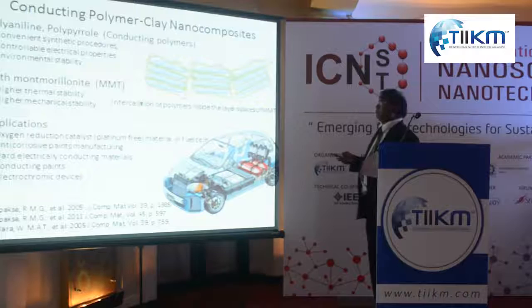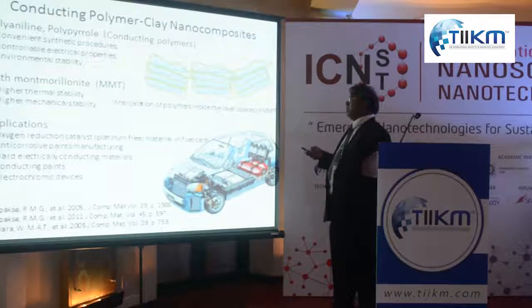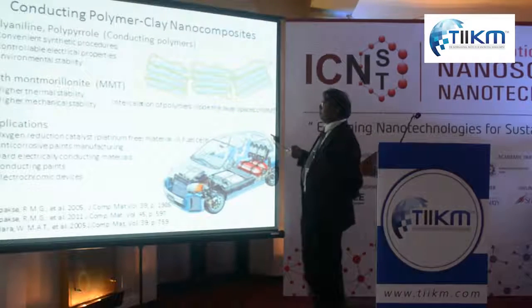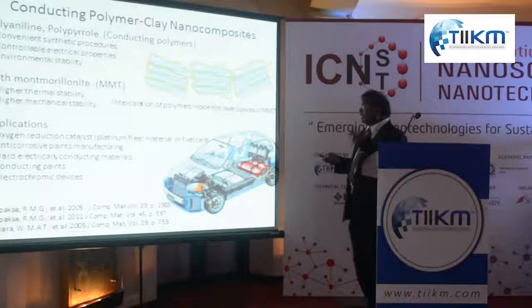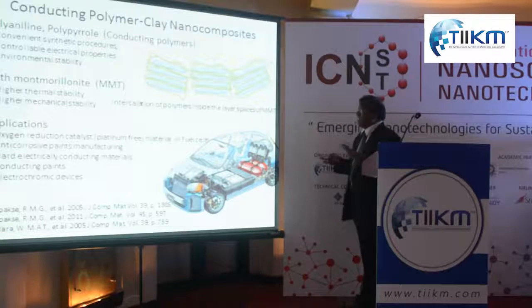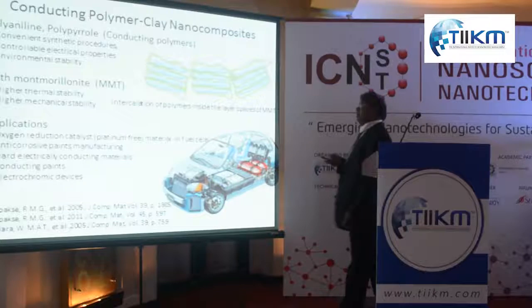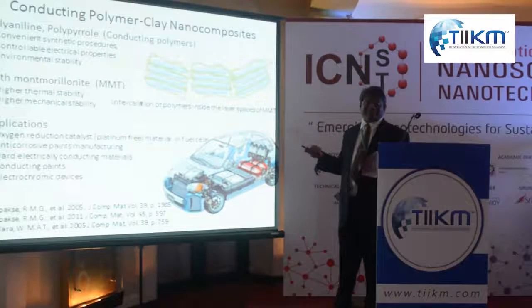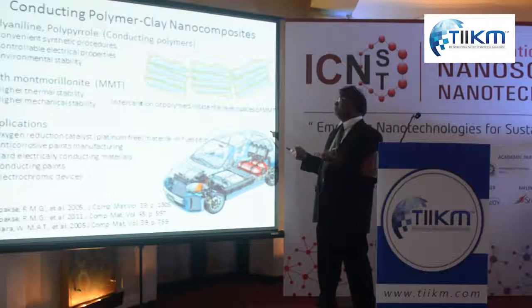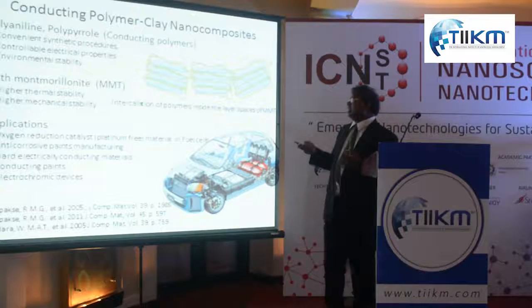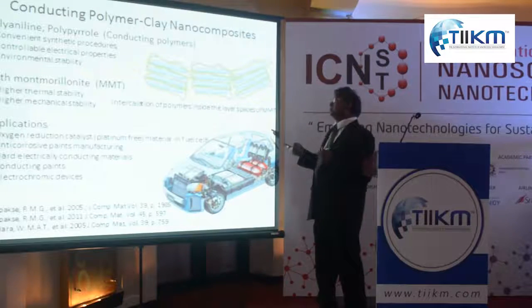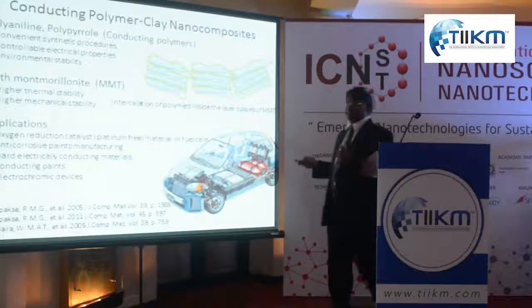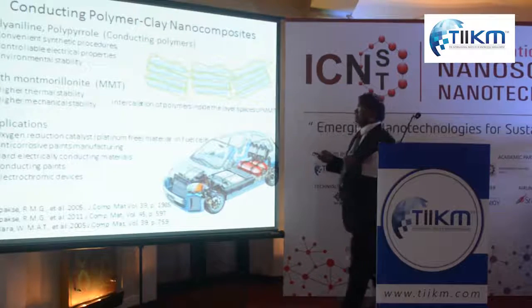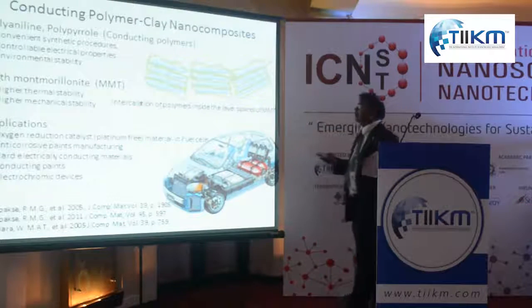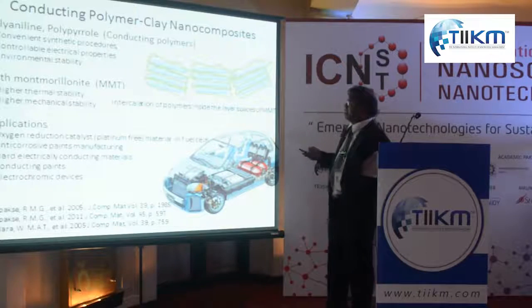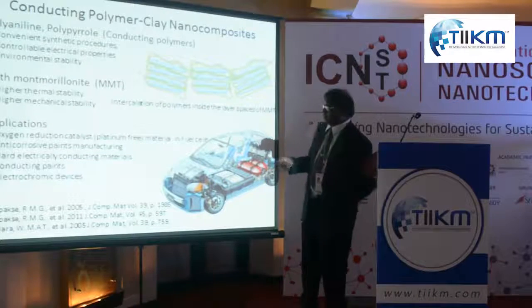And the other importance is that these polymers usually have pockets and voids where gas molecules can go. Now when you put in these clay platelets, they fix into these empty places and seal the material. So if you have a clay polymer bottle to store, say, beer, you can drink it as beer. But with just polymer, say a polythene container, you don't see beer, because there are plenty of pores for oxygen to diffuse through and oxidize the ethanol into acetic acid. So you don't want to drink vinegar. When you have these clay materials, they can seal these pores so that you can make lightweight yet strong materials, with gas barrier properties and many other important properties.